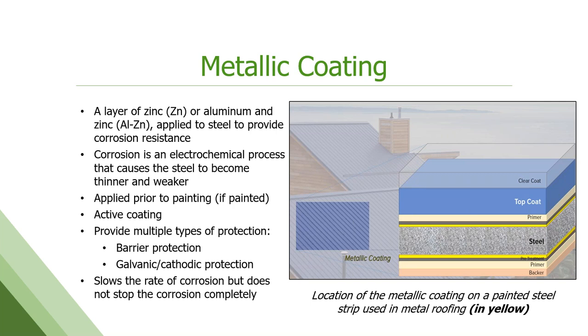So what we have here is a little diagram, a cross section of what a painted zinc aluminum coated steel sheet would look like. Got your steel in the middle there. The yellow would be the very thin metallic coating layer. Then you would have some primer and then your paint on a painted product. This mixture is both an active and a non-active coating. So the zinc portion is actively protecting the base steel, where the aluminum is fairly inert and serves as a barrier protection to the steel underneath. So this combination greatly reduces the rate of corrosion, but does not stop it completely. I mean, this product will over time have some corrosion, but at a much, much lower rate than regular zinc coated or galvanized product.